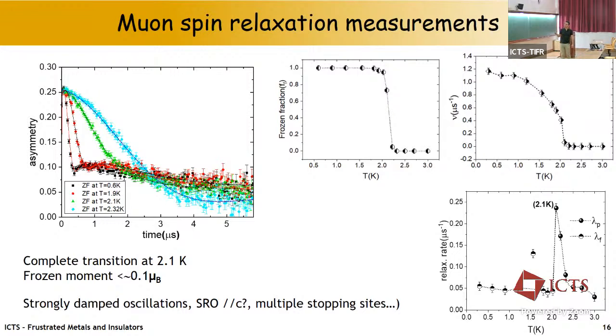Okay. This is the order parameter. I will not dwell too much on that. So that's just the frequency of the oscillation. So that's the internal field, basically. So that's the order parameter for the transition. From the value of the internal field there, we can estimate the frozen moment, which turns out to be quite small. It's only an estimate because we never know exactly where the muon is sitting, and how many coppers it's coupled to, etc. But basically, it will be a small moment below 0.1 μB, which may explain why we didn't see magnetic Bragg peaks in diffraction.